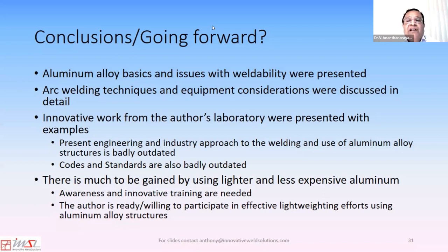I also do spot welding of aluminum sheets to steel sheets without any filler metal, without any plating. And if someone's interested in that, I could work with them on that. And on this question, whether I can weld aluminum 5082 to stainless steel 304, I need joint geometries, thicknesses, and intended use. What are the expected weld metal properties? Again, I can work with you preliminarily on emails. If you send them to me, I can counsel you on those. And if some samples are needed, my laboratory can weld all kinds of dissimilar material combinations. If there's an interest here, I could show photographs of the weld machines in my laboratory.